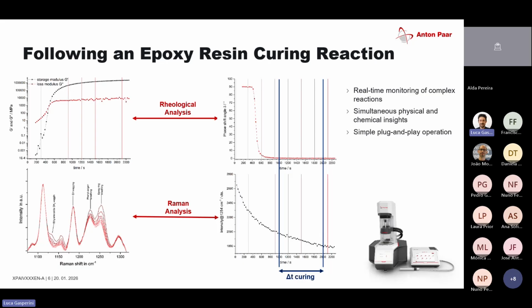So then I have 0 degrees phase angle shift. And if I have something very liquid and something very lazy, for example, and I give it a little bit of push, then it will have a little delay. So in this case, it's viscous, so it's 90 degrees. So between 90 and 0 degrees here, we have a viscoelastic range. So this is what we look at. So if I just take a look at the loss factor here, after 1,000 seconds, it's almost 0 degrees phase angle, so the phase angle shift. So I can say, okay, at this point already, the epoxy resin is completely cured.